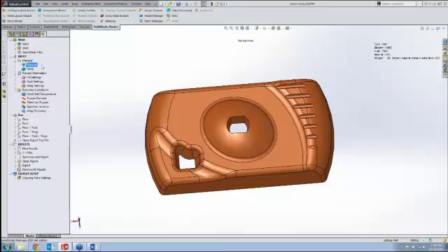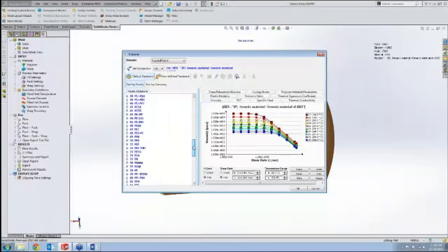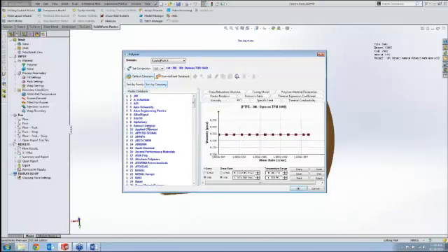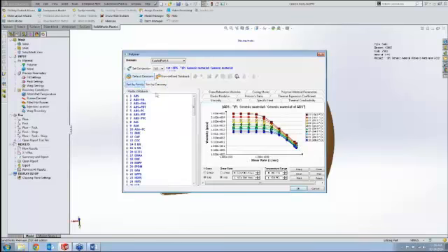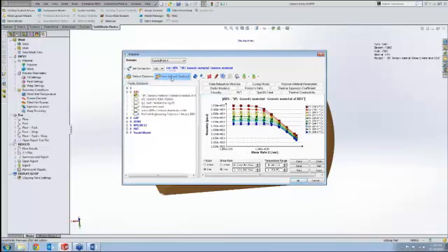You're going to set a polymer material and a mold material. So you can have a series of favorites here, but there's also an entire database of roughly 4,000, a little over 4,000 different plastics. They're grouped by family or by company that manufactures the plastic. And then in all levels of the software, you're going to be able to user define your own materials as well, so that you can lay out custom materials in the software as well. Keep in mind with regard to that, though, there's going to be a fairly large amount of data that needs to get input specifically for the viscosity of plastic, as it is temperature and shear rate dependent.